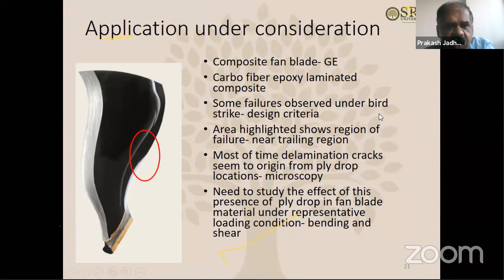Going ahead, the application under consideration, again, was a composite fan blade. The same component that we were considering for this study. This is again a carbon fiber epoxy laminated composite. Some failures were observed under the bird strike design criteria. The highlighted area shows the region of failure near the trailing region.